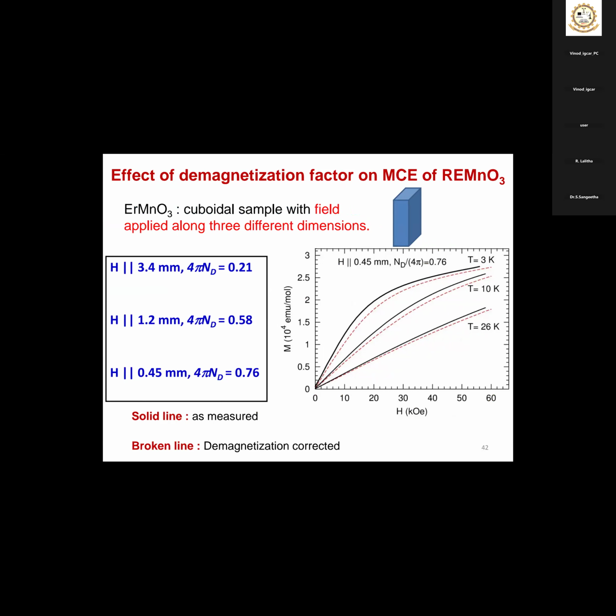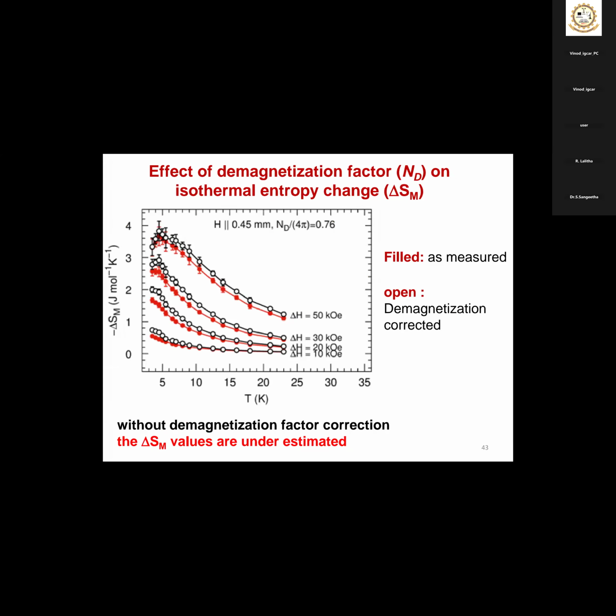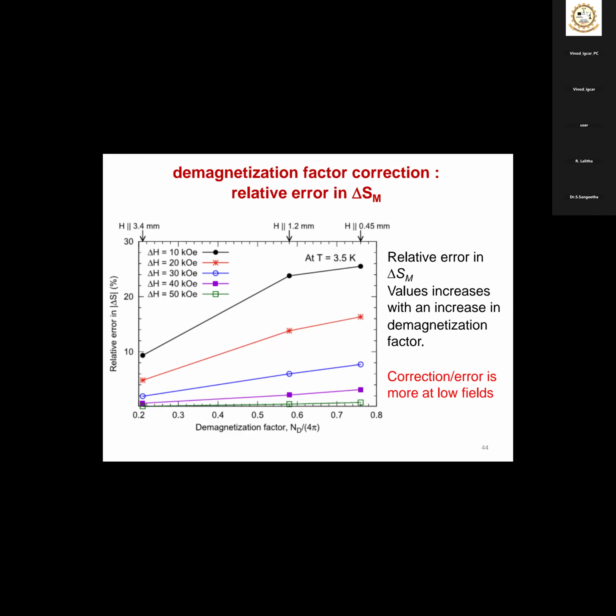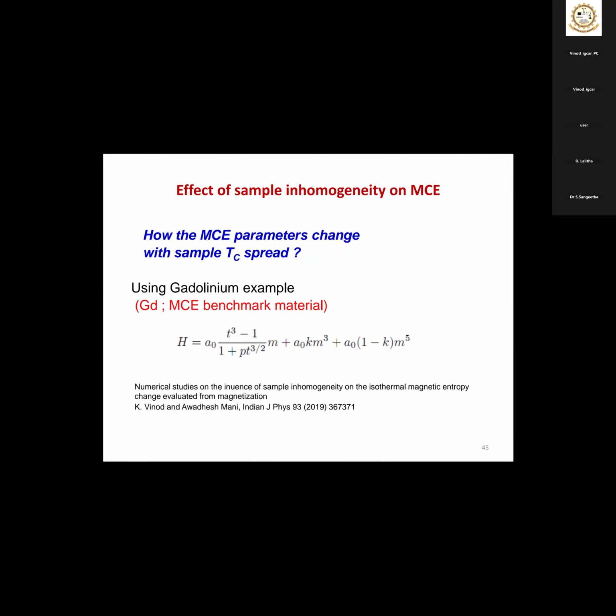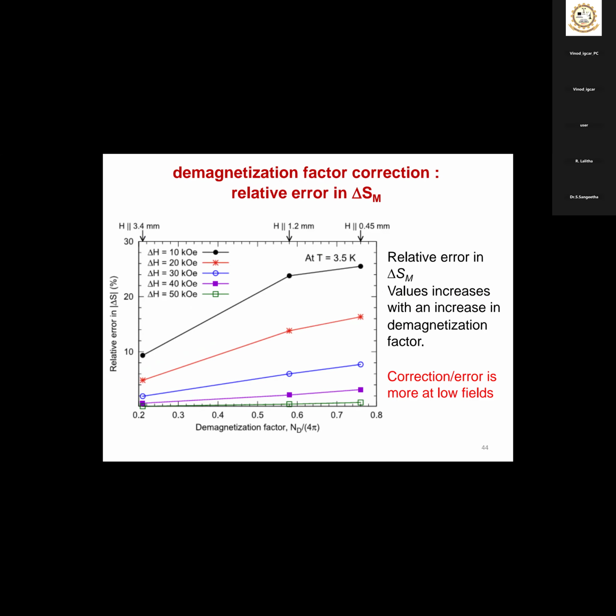You can see for one sample here, for different sample size and different direction, the magnetization is different. Consequently, you have a different delta S versus T curve. So the result I will summarize like this: depending on the demagnetization factor for different geometry for the same sample, you have to apply demagnetization correction. So a relative change will be there in entropy and relative cooling power. So you will have a different entropy.